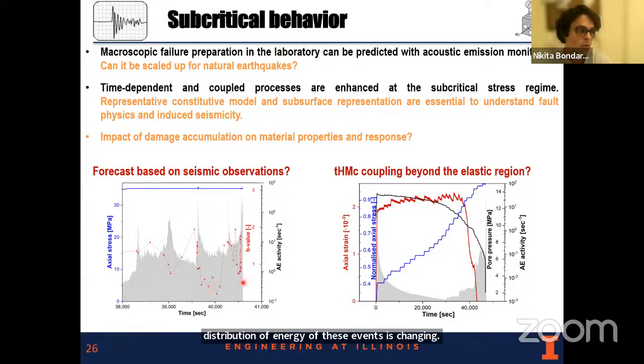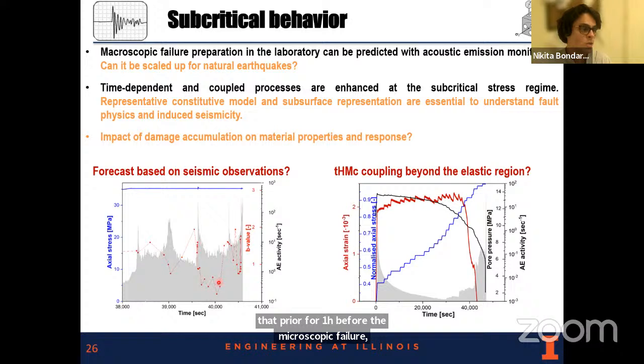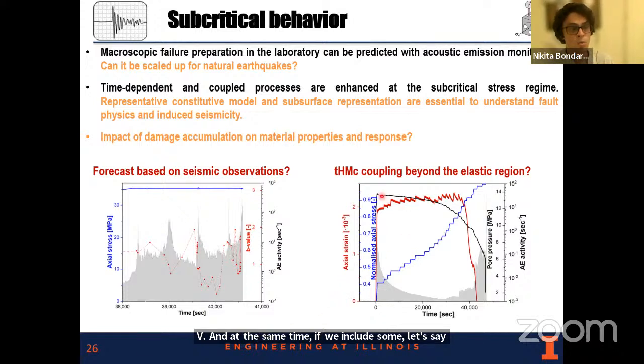This is the so-called B-value in the Gutenberg-Richter law, and we can see that for one hour before the macroscopic failure, which happens at this moment, there is significant variation of the B-value. If we include pore fluid, the response becomes even more complex, with quasi-undrained behavior associated with a drop in pore pressure, which has to be considered to understand the process happening in fault zones. We have to consider these effects.